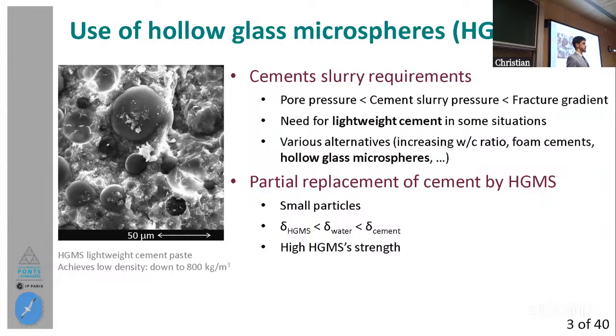So the cementing operations are done when the cement is placed in a fluid state as a slurry, and these conditions have to verify the same requirements as the drilling mud, which are that the cement slurry pressure, which is directly related to the cement density, should at every depth be higher than the pore pressure, but lower than the fracture gradient.